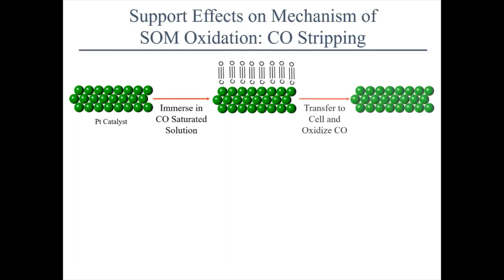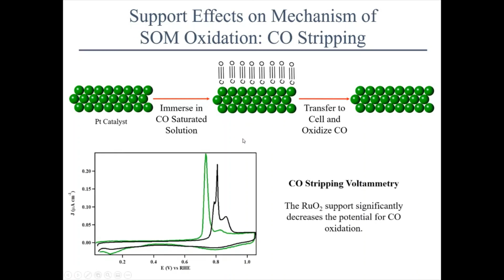Then we transfer that to an electrochemical cell and oxidize the CO off and see at what potential the CO gets oxidized. And so our CO stripping voltammetry showed us that the ruthenium oxide support significantly decreases the potential for CO oxidation. If you look, the peak where the CO comes off is about 100 millivolts lower in potential than that of the carbon species.